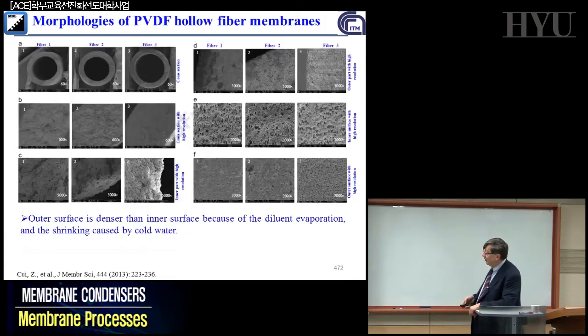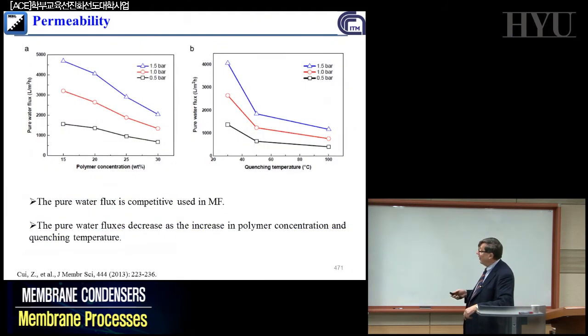And you can see how significant the effect can be in terms of polymer concentration or in terms of the quenching temperature. That means the temperature of the bath, where you make the phase inversion basically on your system. So depending on this parameter, the temperature, from 40 to 60, you can change the transmembrane flux in the system by about 100%. So all these parameters, again, they cannot be any more hard.